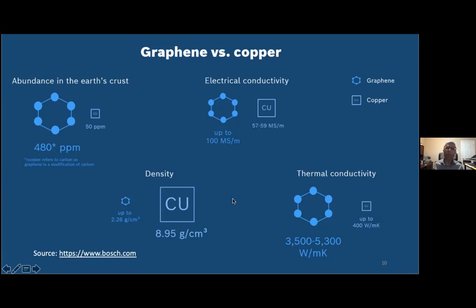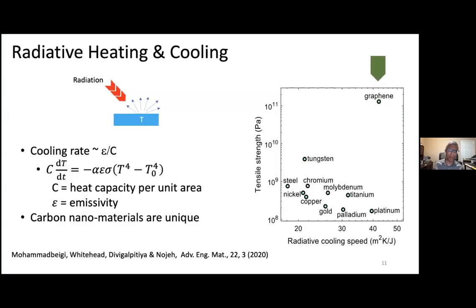So there are a lot of well-known properties, but let me show you something not that well-known, something that we found pretty recently. It's how this two-dimensional material interacts with radiation. So if you dump some radiation onto a material, it gets heated very quickly. And the heating rate is really dependent on what the energy source is. The more energy you have, it heats faster, right? But the cooling is completely different. I'm pretty sure you're familiar with the Stefan-Boltzmann law. It's the T to the power 4 dependence.